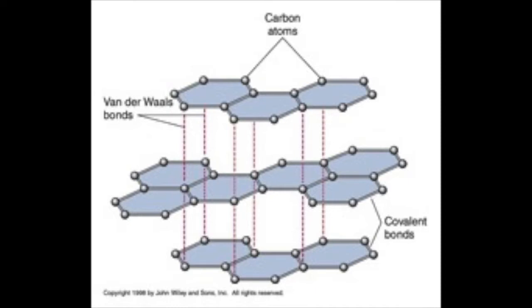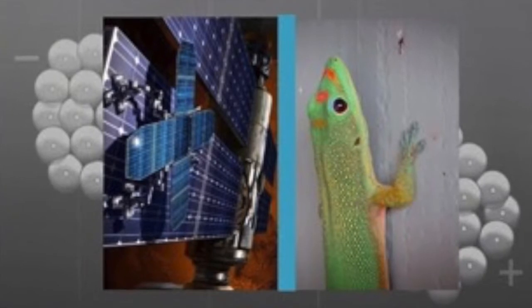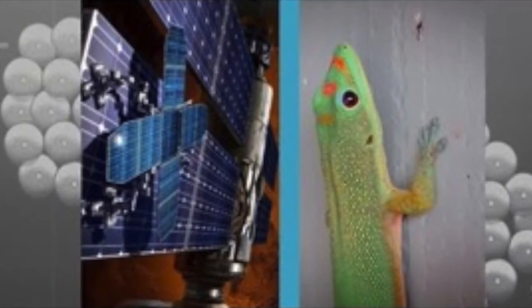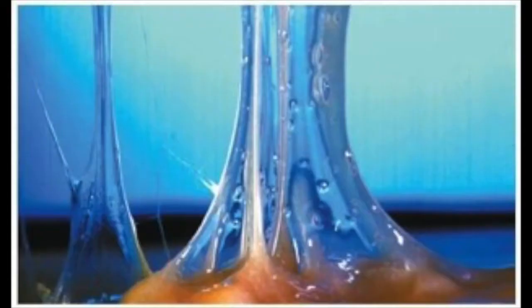These interactions increase the overall force of adhesion. To achieve high shear adhesion strength and release by a transverse load, a synthetic fabric tendon in the center of the adhesive directs the applied force to the center instead of the edge. What sets gecko-inspired adhesives apart from traditional adhesives is that they rely on dry adhesion instead of viscoelastic adhesion. Draping adhesion maximizes conformal contact with the surface while having a high Young's modulus, so there is sufficient elastic stiffness in the directions that force is applied.